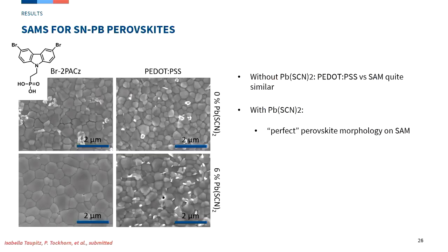We used this self-assembled monolayer molecule in order to have a better hole-selective contact. Also important: for most of the low band gap tin-lead mixture perovskites, you use certain additives, because tin and lead have different crystallization kinetics. In order to homogenize this, you use thiocyanate additives.